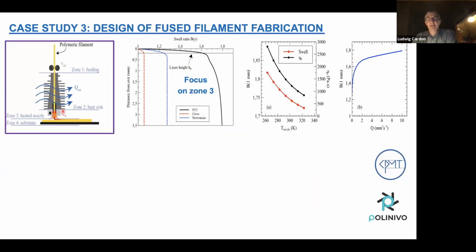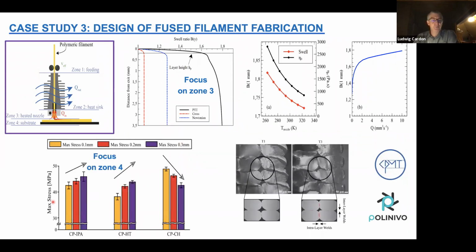So you can understand immediately, to be able to investigate this one, that you need the rheological curves of these kind of materials, of the polymer you want to process. You have to understand the design of the very small nozzles, let's say in this case 0.3 millimeter. And then we define the distance from the exit. So from this position downwards, we define the distance and we find out what's the die swell of the material itself as a die swell ratio. So combined with that one, we also look inside the material for the maximum stress.